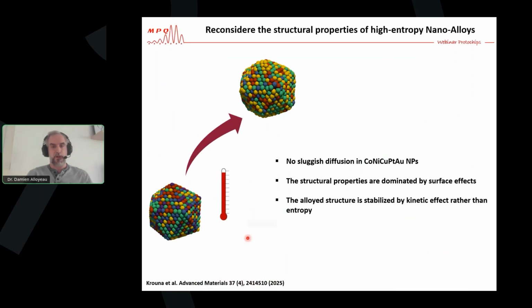So, take home message from this experiment: there is no sluggish diffusion in these high entropy nanoalloy systems. The structural properties are not dominated by the entropy, they are dominated by the surface effect. And as the thermodynamic equilibrium of those nanostructures is the phase separation of gold and copper under vacuum, it means that if you want to fabricate those high entropy nanoalloys with an FCC structure, you need to go fast during the synthesis, because they are still stabilized by kinetic effects. And that tells you that you should not believe everything that you can read in the literature about those systems. You have to study their structural properties.